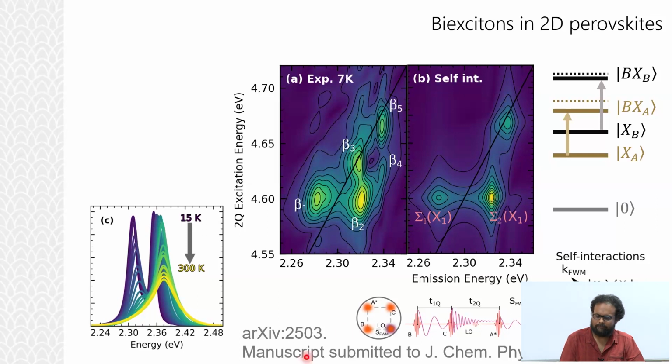In fact, if you go into this paper, in J Chem Phys, we have estimated the biexciton binding with different methods, and we have noted how the 2 quantum method gives the highest precision in the biexciton binding. Okay, so what about the other exciton? It is on the diagonal, but if I go to the other exciton, there is barely only a little shift here. The reason for that is that this exciton has a humongous biexciton binding energy. This one is almost a harmonic interaction. There is not much biexciton binding. It's kind of fascinating to think about.